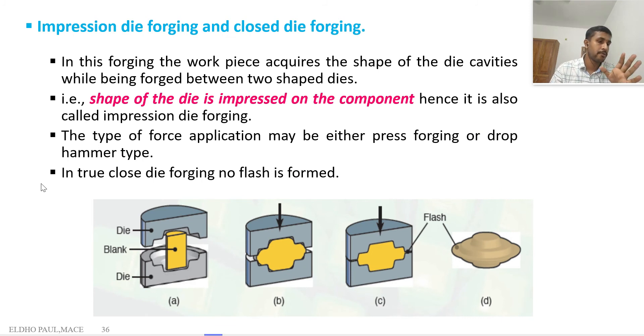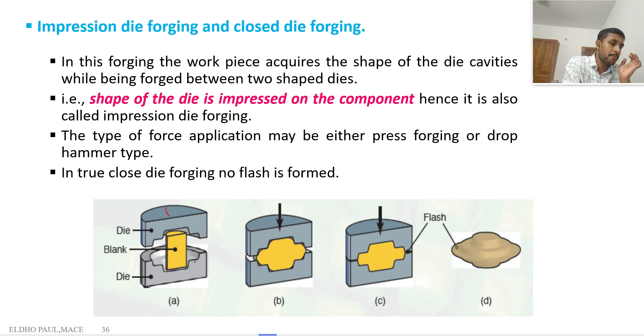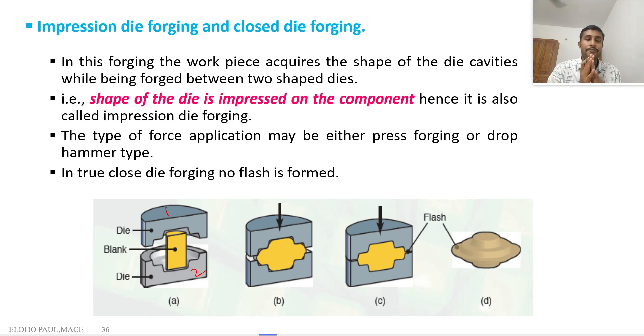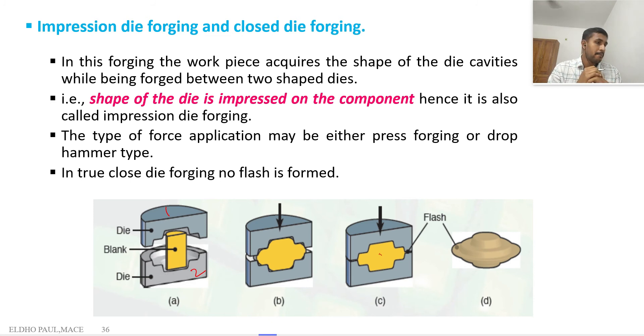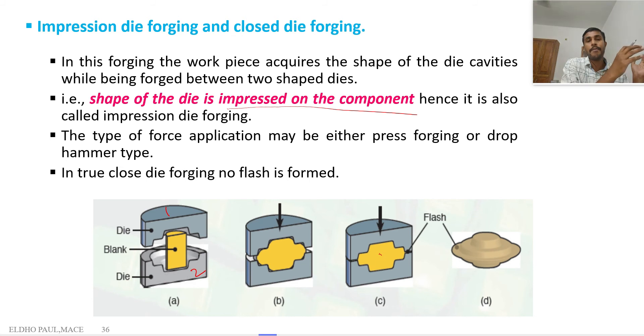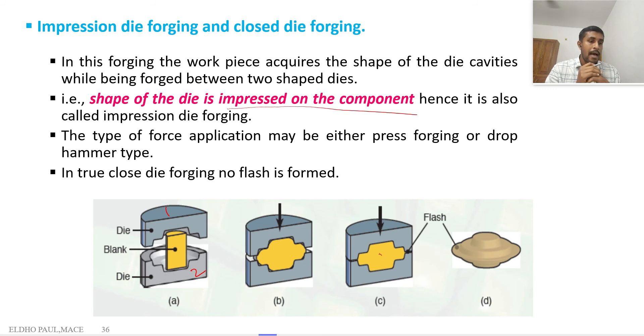The next classification is impression die forging, also called closed die forging. Here we have a top die and bottom die with a cavity between them. The workpiece is kept between the two dies, compressive force is applied, and the workpiece is deformed into the shape of the die cavity. The final product shape and size closely matches the cavity shape. In closed die forging, flash is formed — material flows through the parting line between the dies and fills the flash land and gutter region.